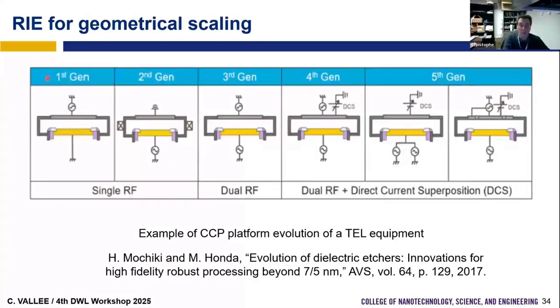Here is an example of the evolution of the CCP platform from TEL equipment. You can see going from the first single frequency generators that were used at high pressure. With this first system, it was not using RIE, it was only high pressure, the substrate here. So we do not use ions. So it was isotropic etching. It was the first system we were doing plasma etching before RIE, but it was mainly isotropic.